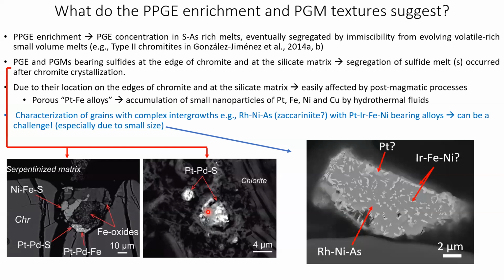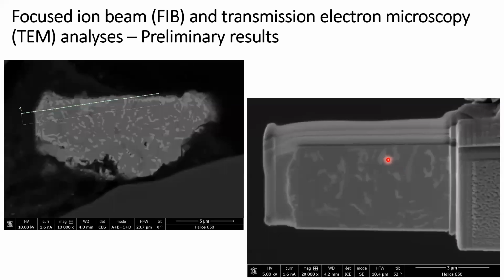And one example of this could be the porous platinum-iron alloys, which could represent the accumulation of small nanoparticles of platinum, iron, nickel, and copper from hydrothermal fluids. And of course, these complex grains, sperrylite for example, are mostly interpreted as formed by secondary processes. But what about these small intergrowths that cannot be studied, for example, by SEM, EDS, or electron microprobe due to the small size? That's why we obtained a lamella of the same grain by focused ion beam and then studied it by transmission electron microscopy.